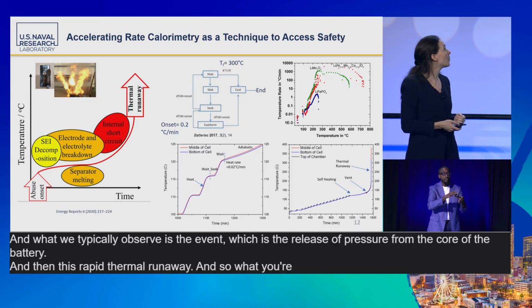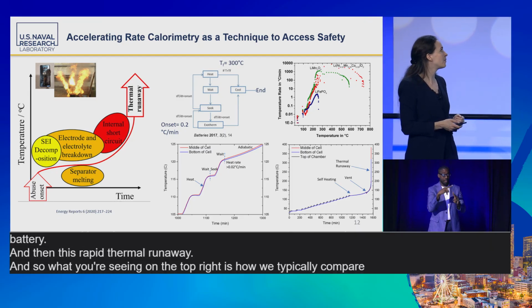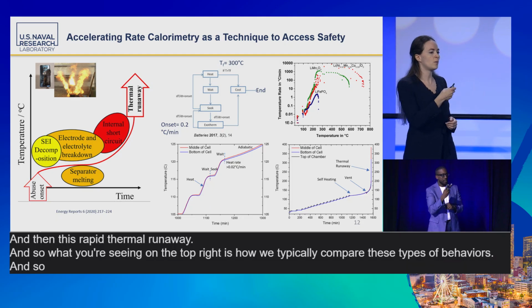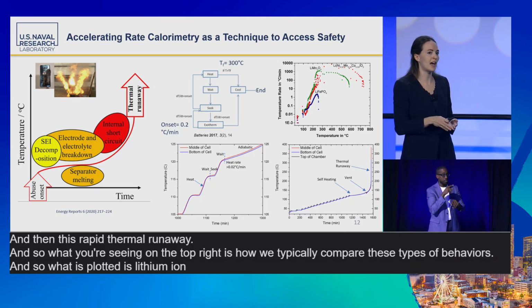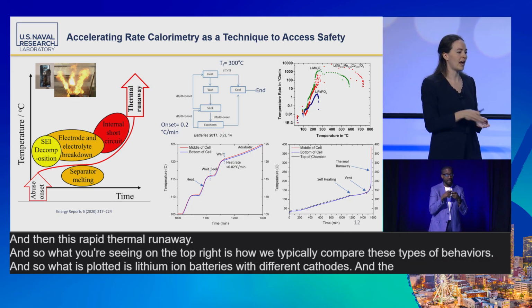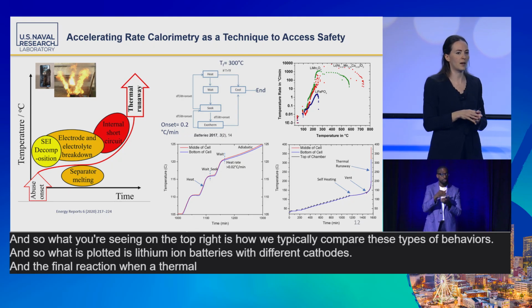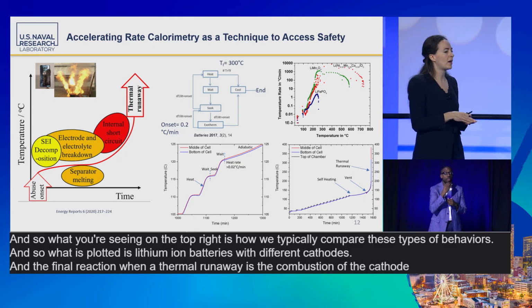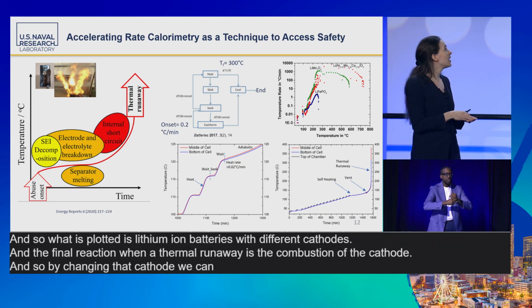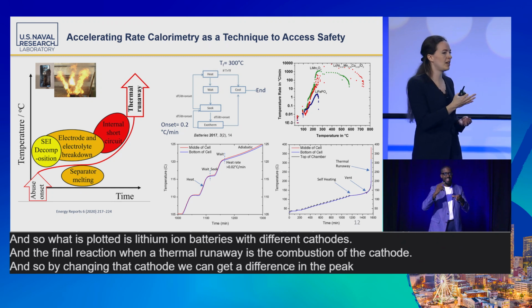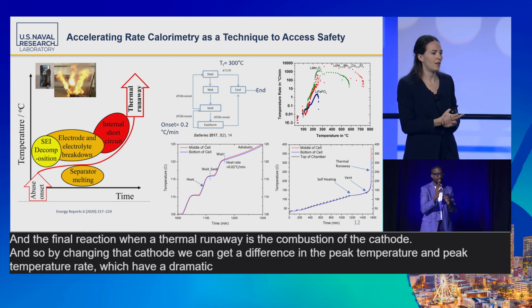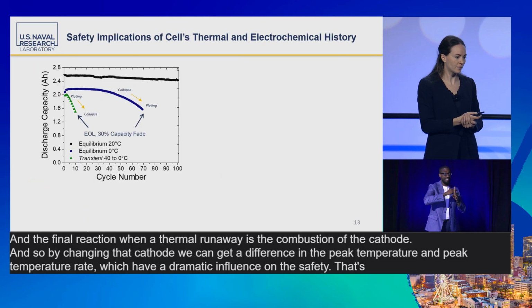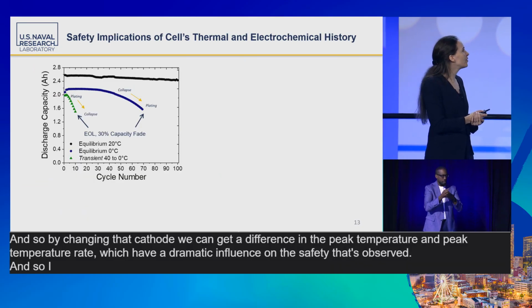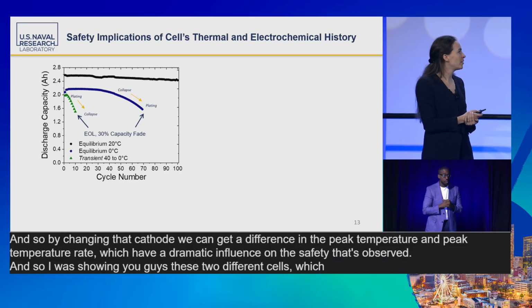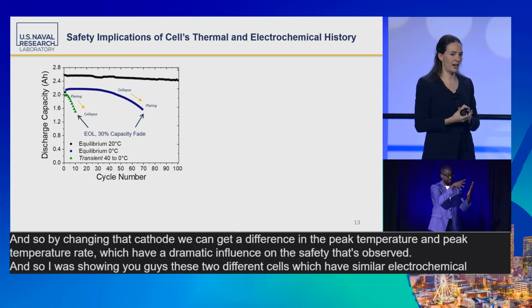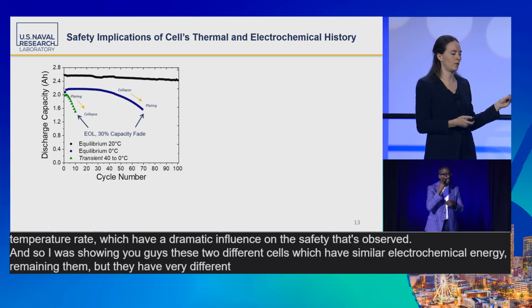What you're seeing on the top right is how we typically compare these types of behaviors. What is plotted is lithium-ion batteries with different cathodes. The final reaction in a thermal runaway is the combustion of the cathode. By changing that cathode, we can get a difference in the peak temperature and peak temperature rate, which have a dramatic influence on the safety that's observed. And so I was showing you these two different cells which have similar electrochemical energy remaining in them, but they have very different thermal histories.